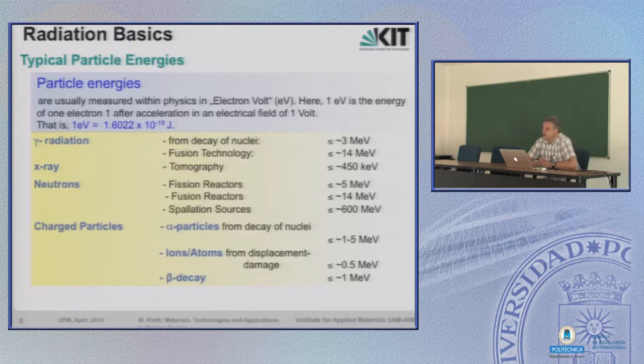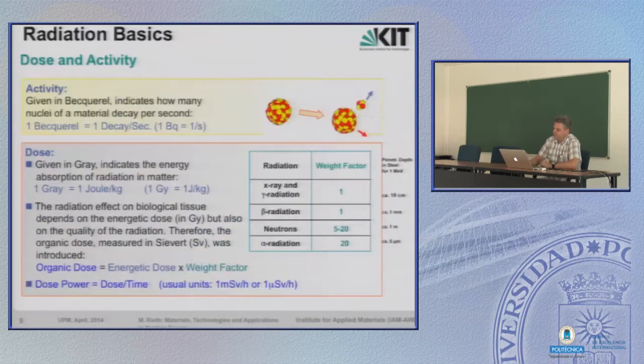And spallation sources, that's very specific sources for neutron production, they have very high energies, 600 MeV. The charged particles, that's alpha particles or helium nuclei, are only 1 to 5 MeV. Single ions from atoms by displacement damage, we will see this later on, are in the range of 500 keV. And the beta decay, which produces electrons, is in the range of 1 MeV.